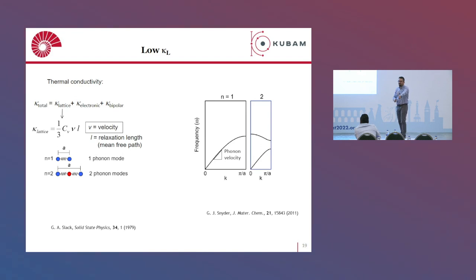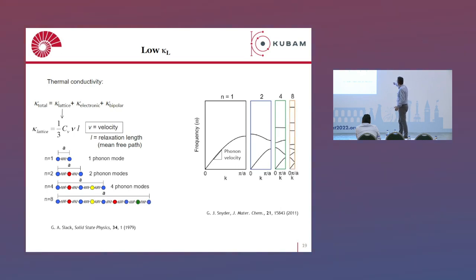Now, if you introduce a secondary atom, you just increase the size of this crystal structure, then this one mode falls into two. If you introduce more, you increase the lattice, and then you shrink the Brillouin zone, and then you can see that you create a lot of optical high-frequency phonons as opposed to low-energy acoustic phonons. And these phonons, you can see that they are flat, which means their phonon velocity is almost zero because the slope is zero.